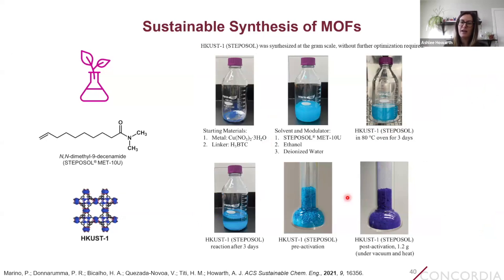And so here's just an example showing that we could make HKUST-1, a copper-based MOF, in STEPOSOL on a 1 gram scale. The nice thing about copper MOFs is that they're always this beautiful blue color, and when we activate them, they turn purple due to the removal of a coordinated water ligand on the MOF node.